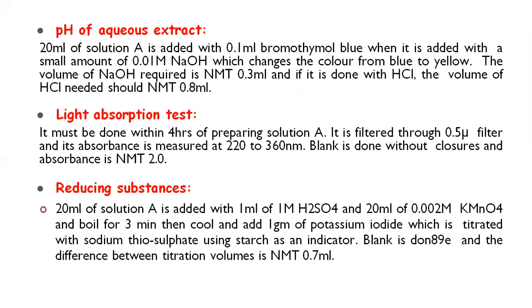Light absorption test. It must be done within 4 hours of preparing solution A. It is filtered through a 0.5 micron filter and its absorbance is measured at 220 to 360 nanometers. Blank is done without closures and absorbance is not more than 2.